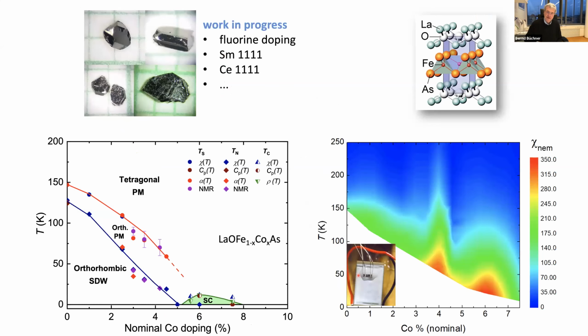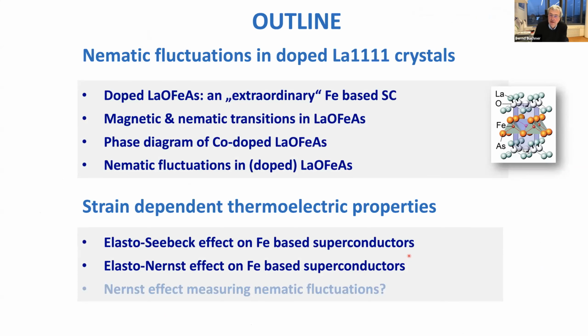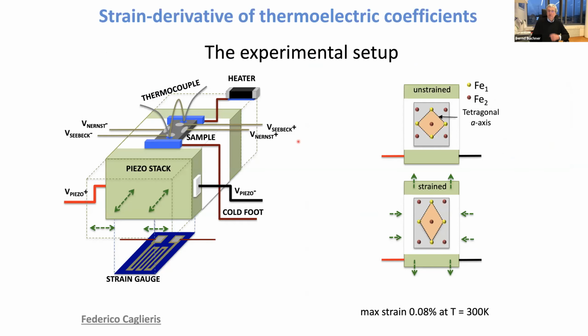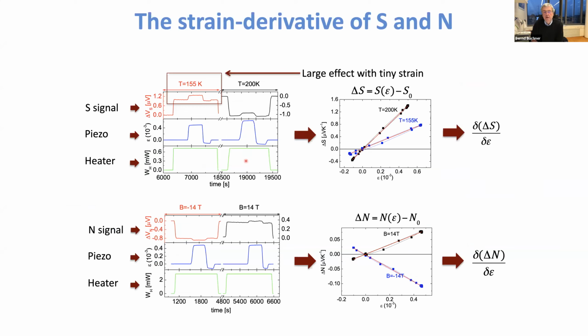Maybe I add a couple of transparencies on these thermoelectric properties, which give you even more information now that these systems are really very unusual metals. So what we are measuring now is we take again such a piezo stack. We take a sample, we apply a temperature gradient, and we measure the thermal power and the Nernst effect. And both of that now as a function of strain. And the strain which we can apply here is tiny, 0.08%, but it's still sufficient to see a signal. And that's shown here, just an example. So that's the way how we do these measurements.